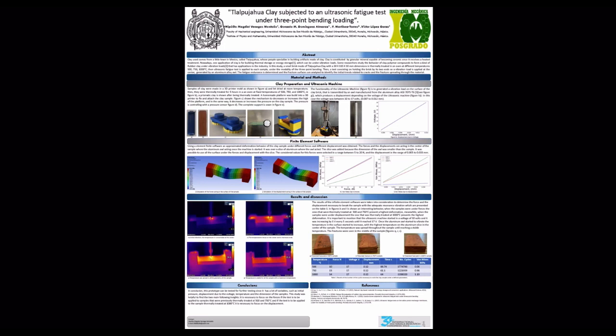The ones that were thermally treated at 500 and 750 present the highest deformation. Meanwhile, when the samples were under displacement, the one that was thermally treated at 1000 Celsius presents the highest deformation. It is important to mention that the ultrasonic machine started in pulses of 10 volts, and it was increased by 1 volt every 5 seconds until it reached 17 volts.